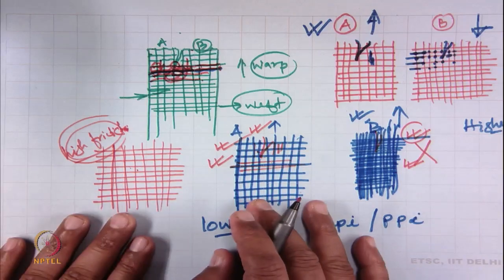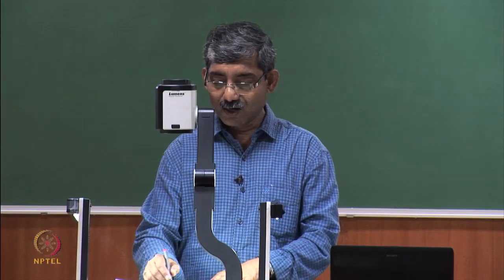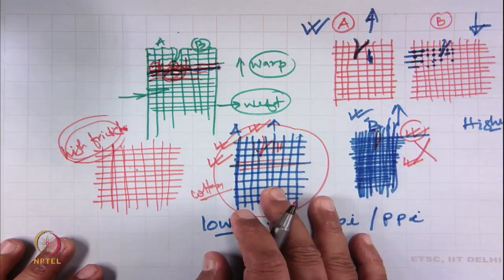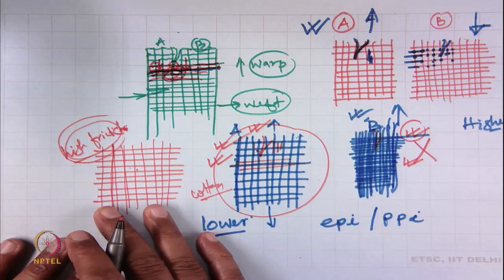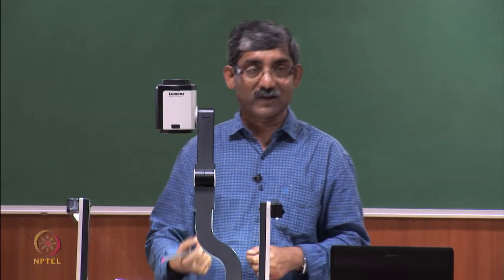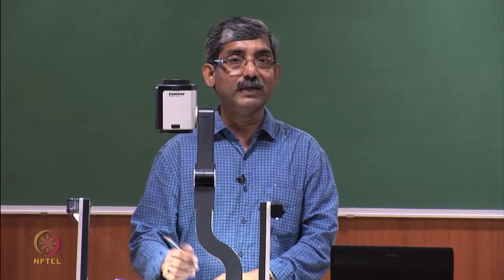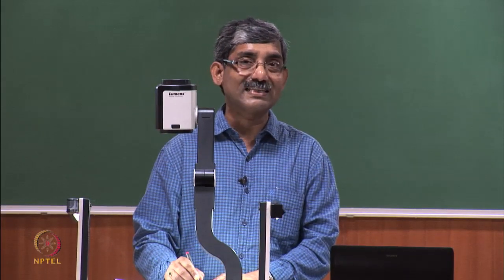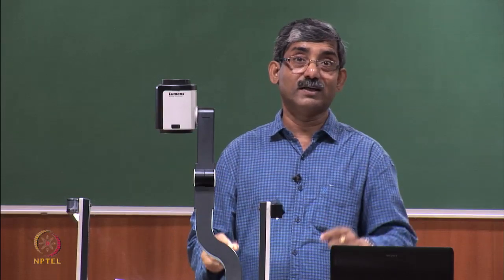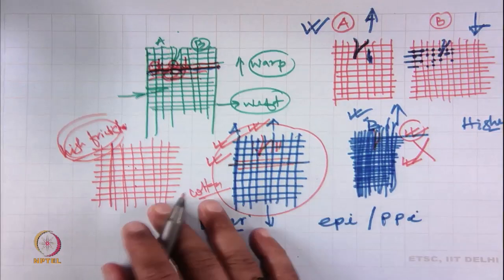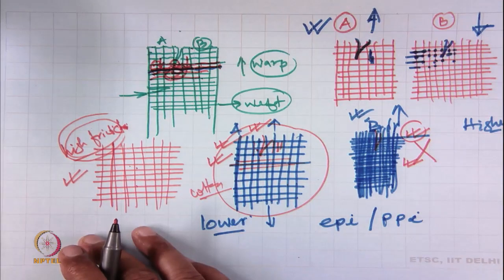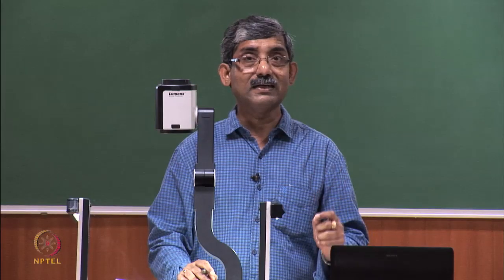This is actually something we can test. We take one normal cotton yarn, gray cotton yarn, and the same construction, and test it with the scoured or bleached one, considering that bleaching or scouring is not deteriorating the yarn strength. So, in case of scoured or bleached cloth, the tear strength will be less than the normal cloth. This is not because of a drop in strength. If we test the tensile strength, this may be the same, if we consider they are same, still the scoured or bleached cloth will have less tear strength because of increase in friction.